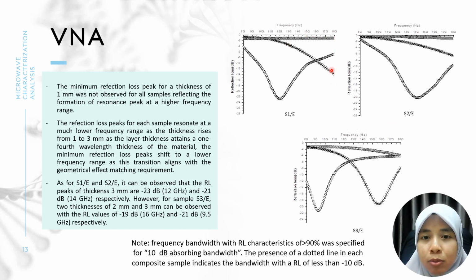So this is 1 mm, 2 mm, and 3 mm. So the minimum reflection loss peak for a thickness of 1 mm here could not be observed for all samples, reflecting that the formation of the resonant peak is actually at a higher frequency range. And the reflection loss peaks for each sample resonate at a much lower frequency range as the thickness rises from 1 mm, 2 mm, and 3 mm. So as the thickness increases, the frequency range is reducing. So next, it is because of the transition aligns with the geometrical effect matching requirement.